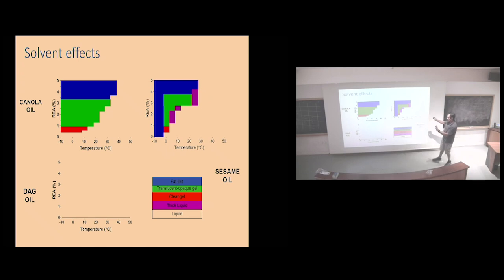And this is not super quantitative state diagrams, but if you make your gel in canola oil, you get the red, which is the good part of the gel, right? Now, if you put it in sesame oil, you have shrunk it. Now, sesame oil, have you eaten it? It has a lot of brown stuff, polar components in it. If you actually measure the polarity, now you're going to dissolve the surfactant, the hydroxystearic acid, more. And so if you dissolve it, now you have less gelling agent. You have to mind the oil you put it in.